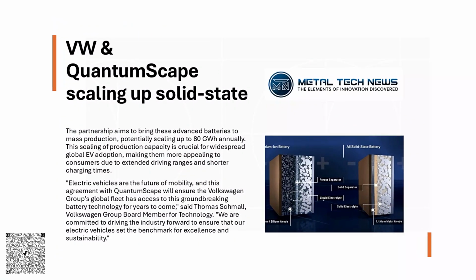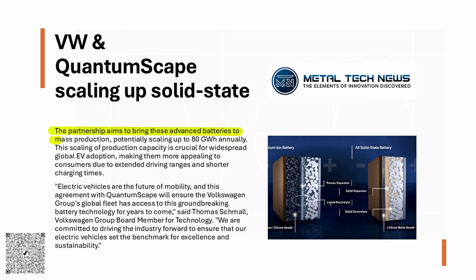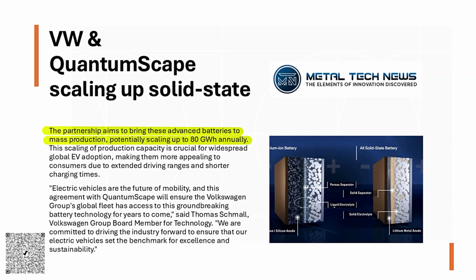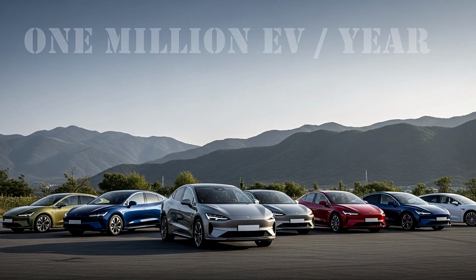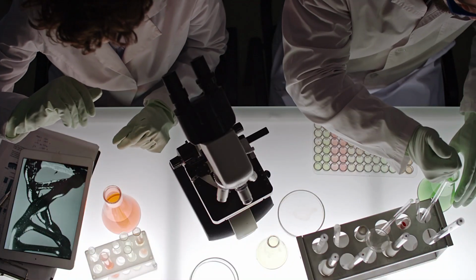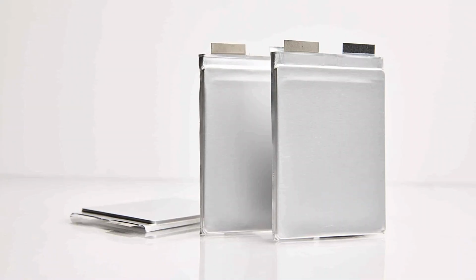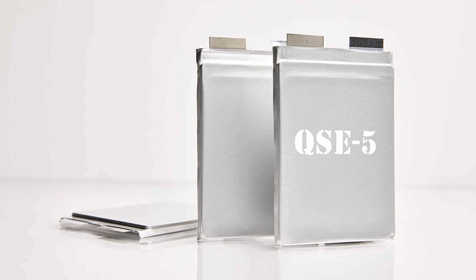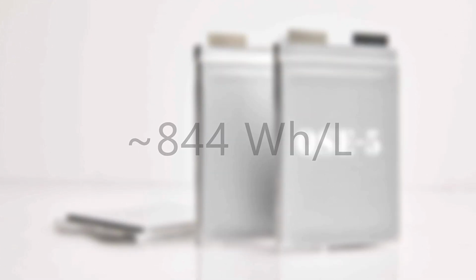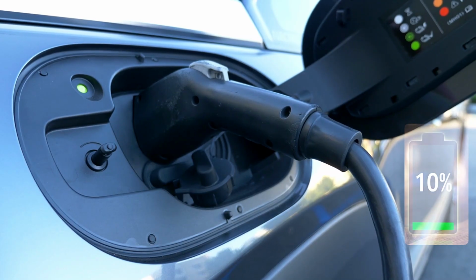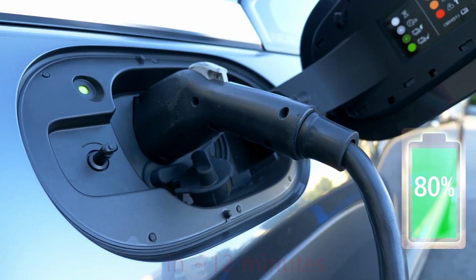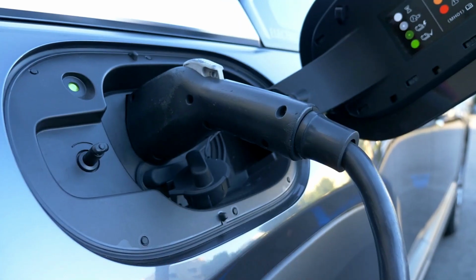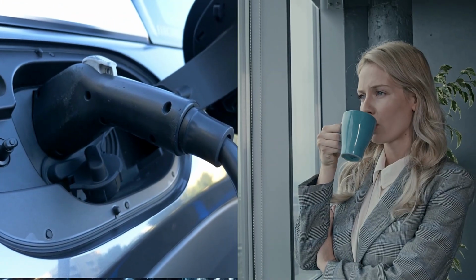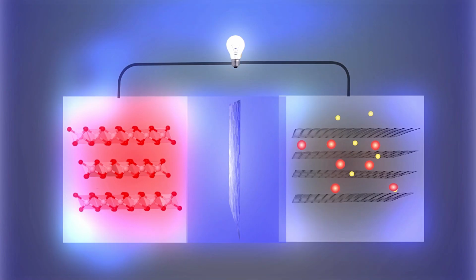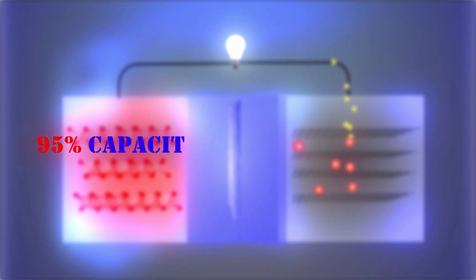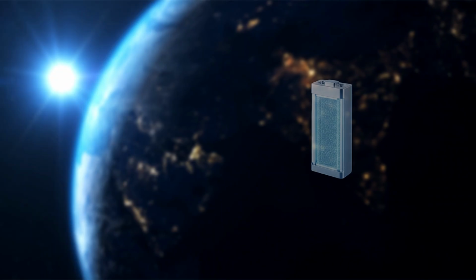A VW QuantumScape partnership is aiming at 80 gigawatt-hours per year of all solid-state cells, enough for 1 million EVs per year. In lab tests, QuantumScape's own new solid-state cell, QSE-5, reached nearly 844 watt-hours per liter and charged from 10% to 80% in about 12 minutes. That's equivalent to a full charge in the time it takes to drink a coffee. It also demonstrated nearly 95% capacity after 1,000 cycles.